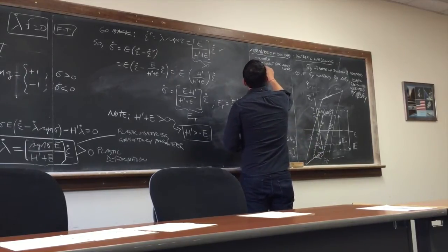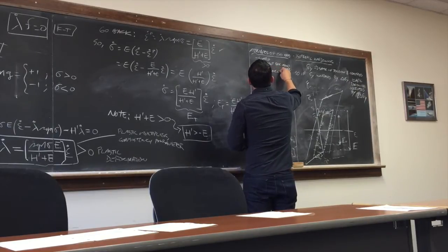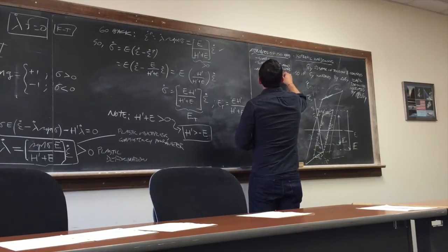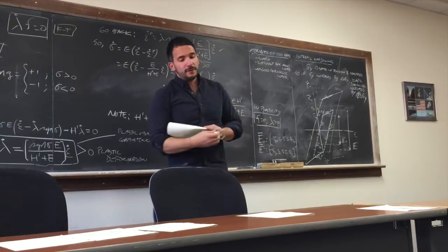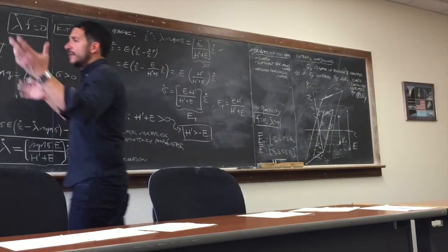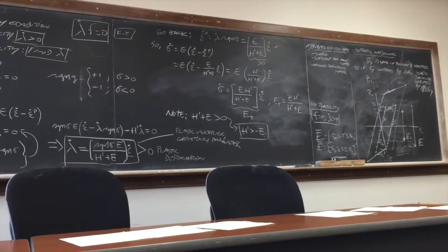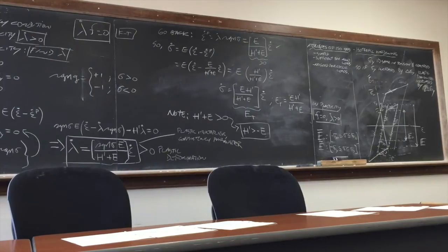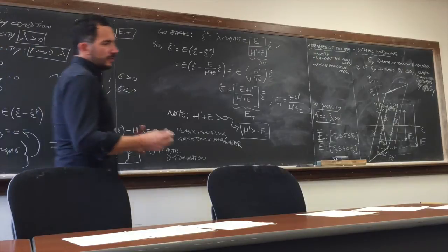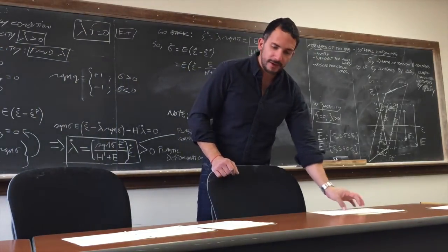However, it's not good for cyclic loading. If you want to use it to simulate the behavior of a structure after an earthquake, not good. It's going to make you increase your elastic region in a way that is unnatural. If you want to simulate the cyclic loading on an airplane, not good. And so on. So be careful with isotropic hardening. Just make sure that you always use it for monotonic loading, and things will be okay.